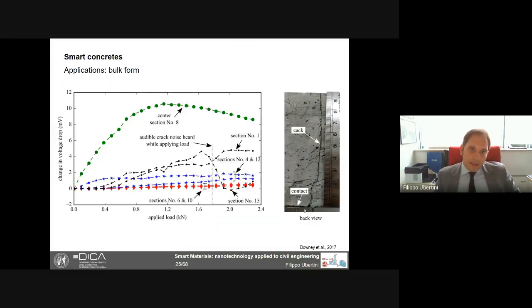So we increase the load that in this diagram is in the x-axis, and we measure the voltage drop across all pairs of electrodes that is in the y-axis. With the green line, you see what we get at the mid-section of the beam. So, of course, is where we have the largest variation in voltage, which means the largest variation in resistance of the material. And this variation in voltage drop is linear with the load until a certain point where we reach some plateau. This graph resembles a little bit the plastic behavior of the cross-section.